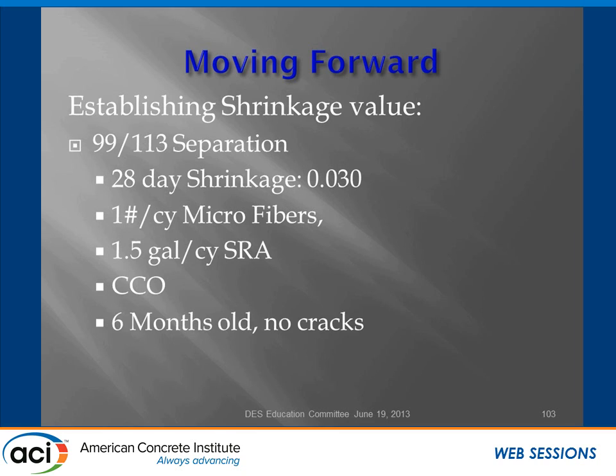So to try to establish that, rather than have a one-size-fits-all shrinkage-reducing admixture dosage for all parts of the state, we think we prefer to go with a performance specification, a 28-day shrinkage value for what you need to pre-qualify your concrete at. So with that effort in mind, we're still evaluating what that target ought to be.